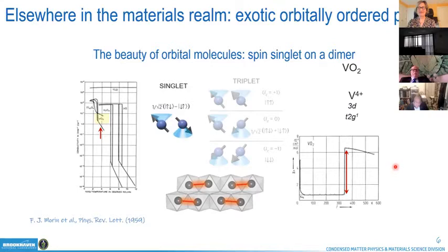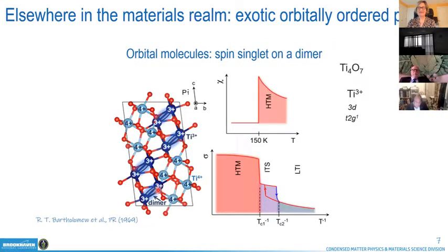The signature of this spin singlet state is a drop of magnetic signal in magnetic measurements at the transition, and the formation of a very short metallic bond that corresponds to this spin singlet dimer. And in this particular case, there is of course a high temperature metallic to low temperature insulating transition. Now, this is not an isolated case. We can see that it happens also in Magnéli phases, like so.